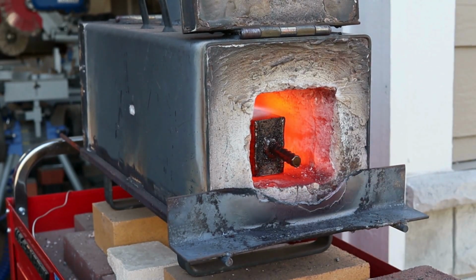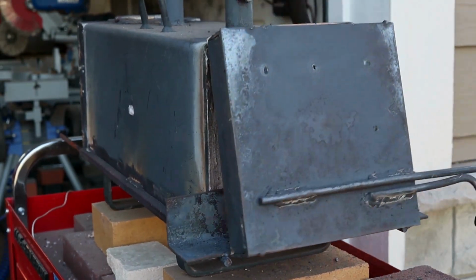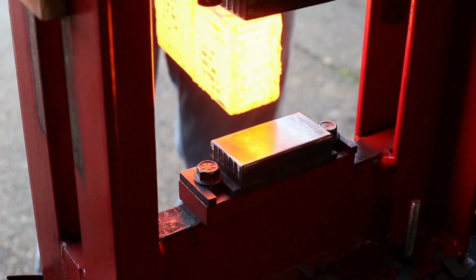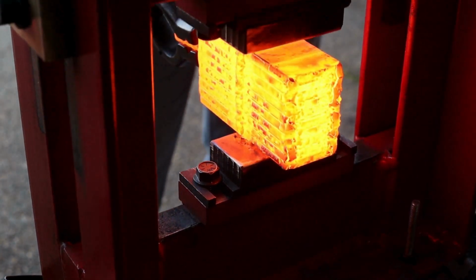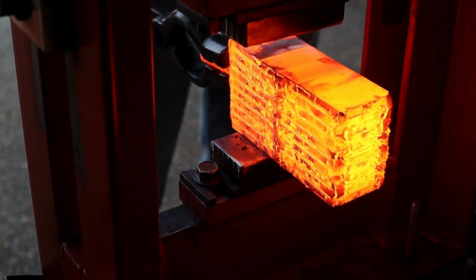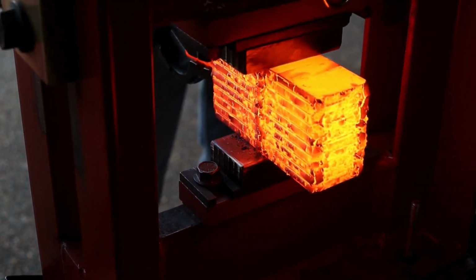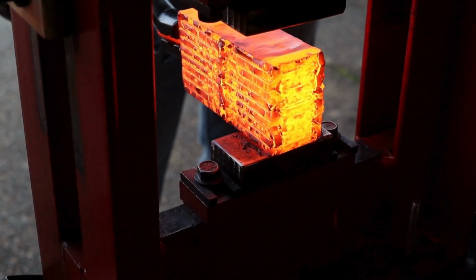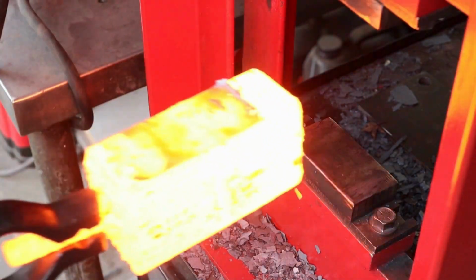If you're trying this method for forge welding, it's important that you don't move the billet around at all once you put it in the forge for that first heat. You can imagine how fragile that carbon layer is, and if you're flipping the billet over or moving it around, you'll most likely create cracks and allow oxygen in between the layers of your steel. So put it in the forge and don't touch it again until you're ready to set the welds.